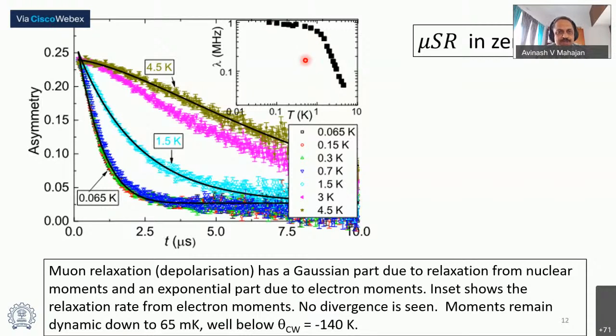So once again, there is no telltale sharp peak in the relaxation rate, which would be expected for long-range ordering. Also, there is no decrease to very low values if you had static moments at low temperature. So these basically show that you have magnetic moments and they remain dynamic down to lowest temperatures in spite of strong antiferro interaction. Okay, so the lowest temperature is 65 milli-K. You compare that with the exchange coupling, which is of the order of 70 Kelvin.